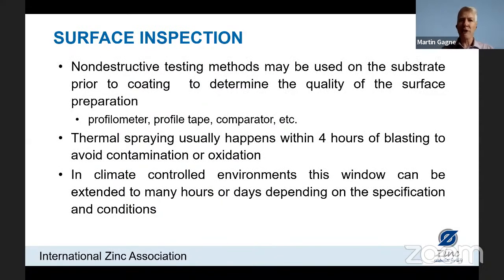Now, after we blasted the surface and we want to ensure the quality of that surface before we apply the zinc, we do some non-destructive testing. This is generally a tape test. We try to apply the thermal spray within 4 hours of blasting, but if we are in a controlled environment, this window can be extended many hours or days.